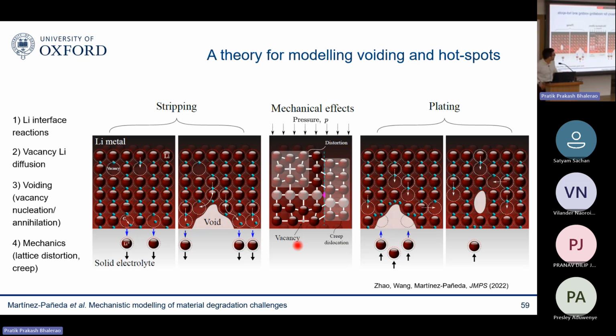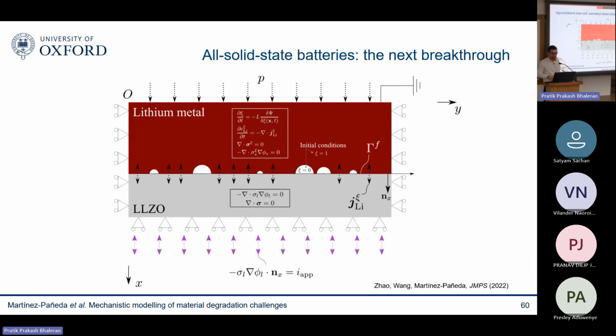You also have lithium diffusion within the metal, vacancy diffusion. Again, you can couple that with a transport problem. You're voiding, so a nucleation and annihilation of vacancies that generates voids, and those voids are going to evolve in time, which you can capture through the phase field mechanism. And then mechanics. Mechanics plays a big role, not only due to lattice distortion, due to the transport, like the chemical strains that we discussed before, but also because the main hypothesis in the battery community is that in order to prevent those voids from growing, we can apply a stack pressure. Lithium metal is like toothpaste. It's very soft, so if you apply a stack pressure, you'll close those voids.